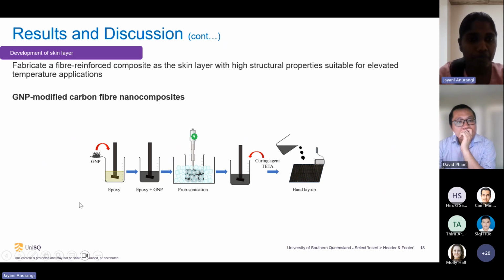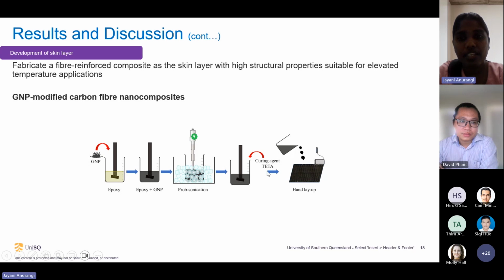For that, firstly, I dissolved GNP in the bisphenol A epoxy. Then the solution was manually stirred for 10 minutes, and then the solution was sonicated for around 30 minutes. And then TETA hardener was used as the crosslinker.